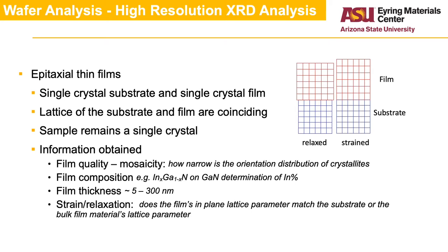The information one can obtain from a high-resolution measurement on an epitaxial film includes: the film quality, where we measure the spread in orientation of the film's diffraction spot; the film composition, when working with solid solutions; the film thickness; and finally, the strain remaining in the film as a result of the mismatch between the substrate and the film's lattice parameters.